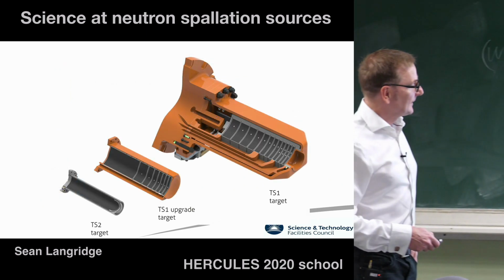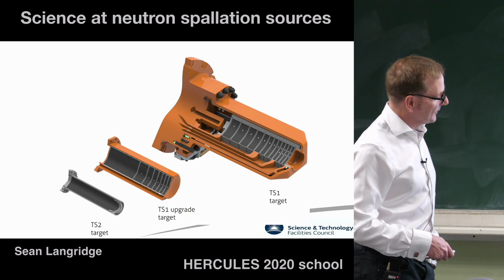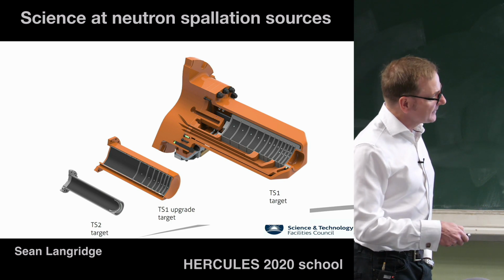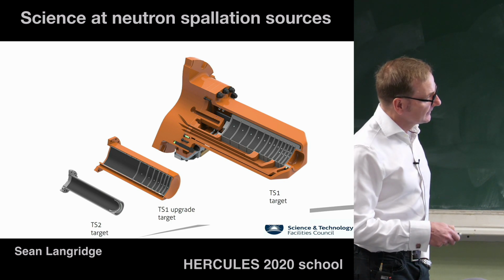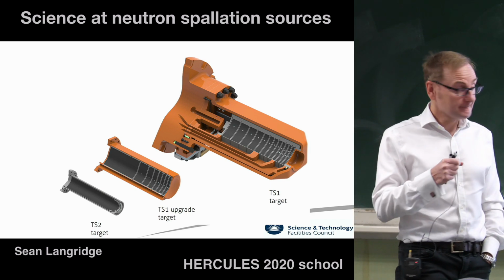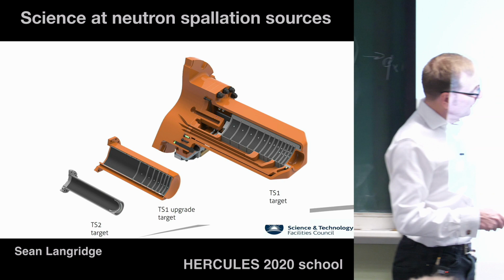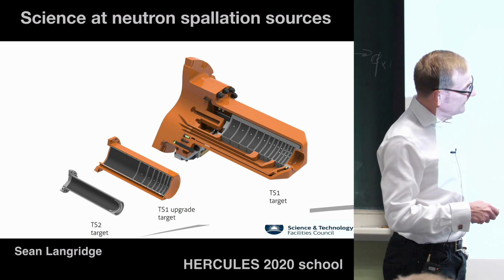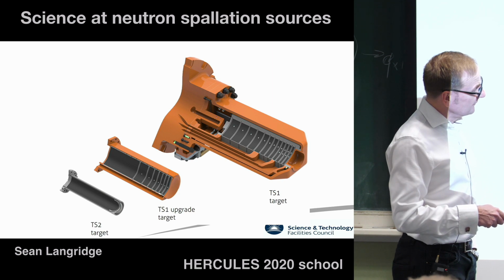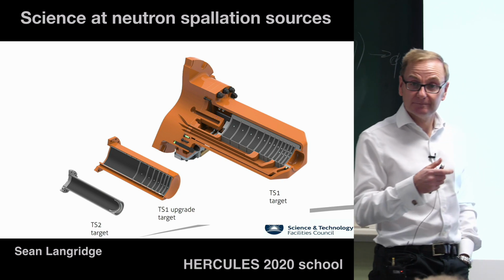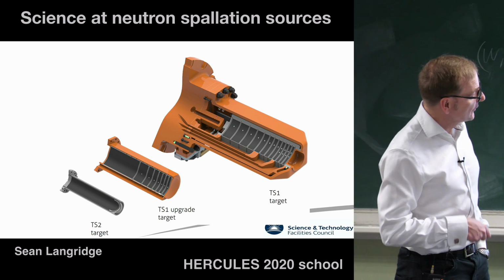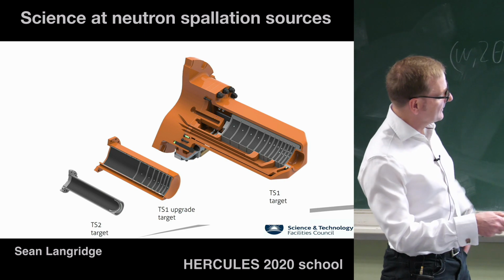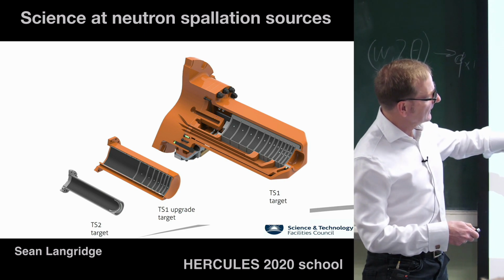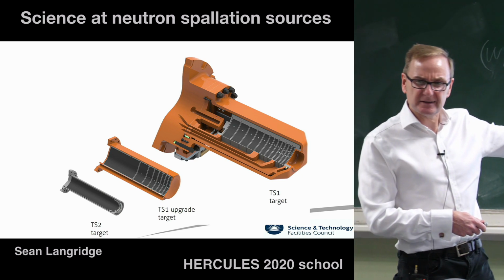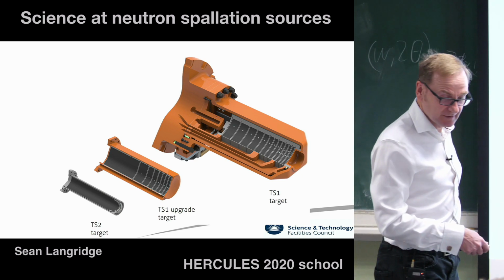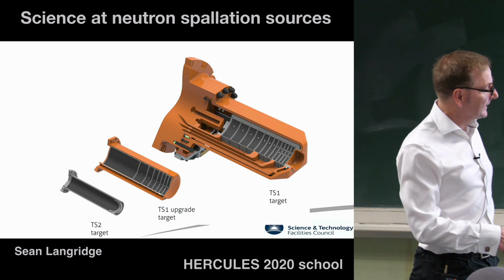Very straightforward. Let's have a look at a little bit more detail at what the target looks like. So this is the existing target on TS1. This takes 160 kilowatts of proton power. And what it consists of are blocks of tungsten, which is the dark grey here. It's tantalum clad, and these little channels you see here are for cooling, and the little holes are for thermocouples. So proton beam comes in here. Actually, it's probably half the size of that in reality, something like that. So that's the existing target station that is beaming away as we speak.